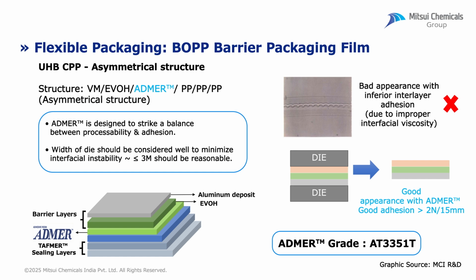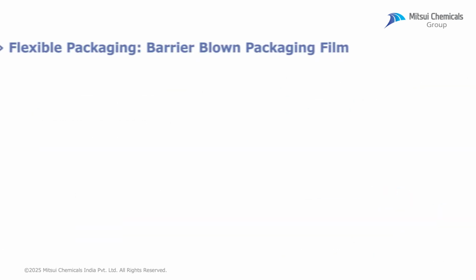based oxygen barrier resin. Admer provides balance between processability and adhesion, resulting in good appearance with the cast process. Admer is also well commercialized for blown film applications.